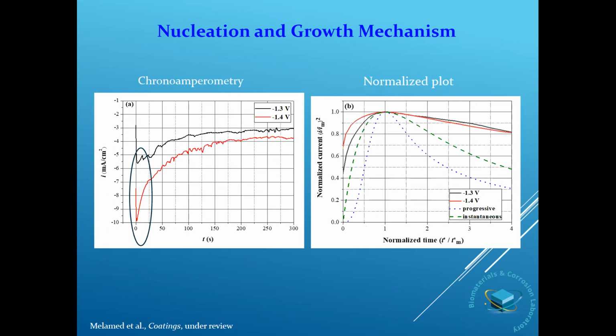So figure A presents the experimental chronoamperometric transients at various applied potentials, while figure B presents the normalized curves for two different applied potentials and the comparison to the Scharifker-Hills models. From figure B, it is evident that the deposition of aluminum on nickel is characterized by instantaneous nucleation. Compared to the instantaneous nucleation model, the higher experimental normalized currents may result from parasitic currents as well as from the inhibition effect associated with free chlorine ions in the processes of reduction and the change of species and complexes in solution. Cyclic voltammetry, chronoamperometry, and the X-ray photoelectron spectroscopy all indicated in our study possible effects of a side reaction.